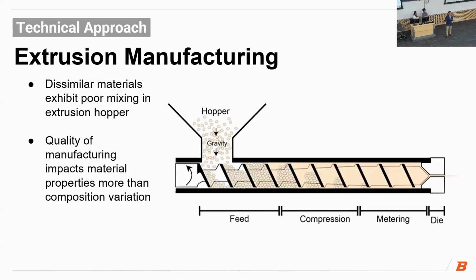We did this predominantly through a technique called extrusion manufacturing. It's the most common form of manufacturing polymers, and getting it right was essential to our project because we identified that the single greatest impacting factor on a wood plastic composite's material properties was the ability to manufacture it correctly and completely. Specifically, we accomplished this extrusion manufacturing by processing the 2 waste streams that Boise Cascade provided us, putting them in the hopper, which gravity fed the extrusion auger that were then heated, compressed, and metered into a die, or in our case, 1x1 board molds.